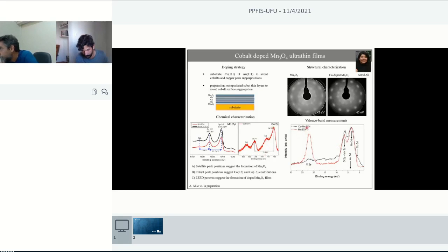of these films, non-doped and doped, close to the valence band. And then there in the valence band, here's the Fermi position. We see a bump here that we can assign to the cobalt 3d.